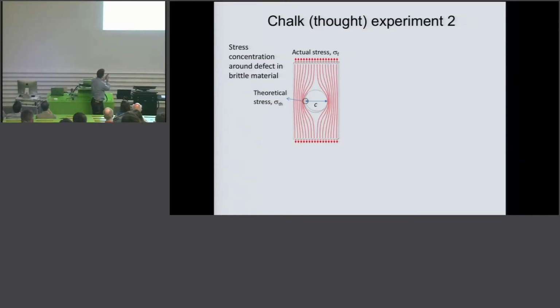What happens is that all the stress lines that come at this region basically cannot transmit their forces to the other end, right? So everything has to come around the defect, which means you will have a stress concentration in this area, which is not a problem for a metal, which will locally deform plastically through motion of dislocations, but it's a big problem to a ceramic material which cannot deform plastically. And that is the reason why the strength of a brittle material is never a material property. It has to consider also the size of defects, right?